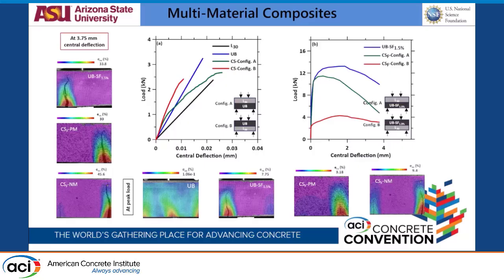We tested for the opposite section also, where we put L30 on the bottom and then put SF on the top, because there might sometimes be a negative moment coming in. The L30, not having a fiber, kind of breaks, and this more or less acts as a reduced section. Let's say the beam size is 60 mm that I'm using. The response will be equivalent to a 30 mm UHPC SF 1.5% beam.